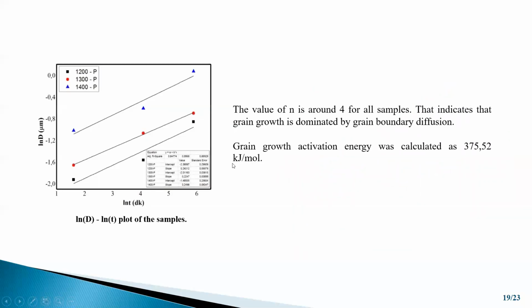The n exponent in the kinetic equation shows which mechanism is dominant during sintering. The slope of the ln D versus ln t plot gives the value of 1/n. The value of n was found to be around 4 for all samples, and that indicates grain growth is dominated by grain boundary diffusion. The highly effective nature of the grain boundaries provides the driving force for sintering, and grain boundary diffusion occurs faster than lattice diffusion, and it contributes to the densification of the material rather than grain growth.